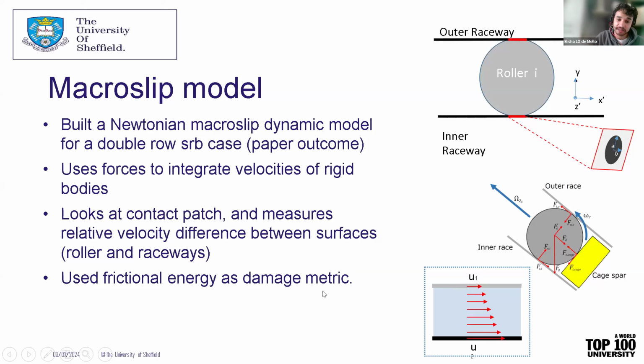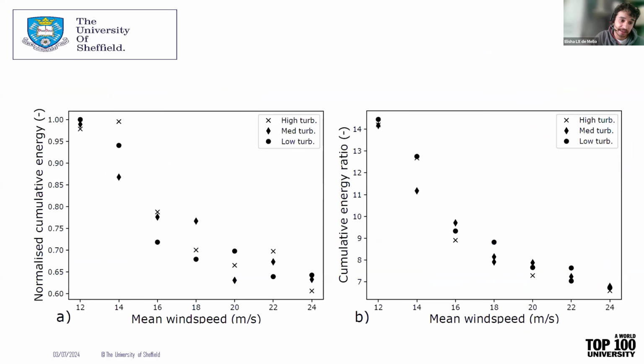So this model directly investigated slip, and it found that when we investigated this frictional energy, these are normalized results here, that we got higher frictional energies at lower wind speeds. And this actually corresponded to the operational thrust strategy of the turbine, as the turbine started to pitch its blades after that, and we got a higher radial force and less thrust force. So that was an initial result of that study.